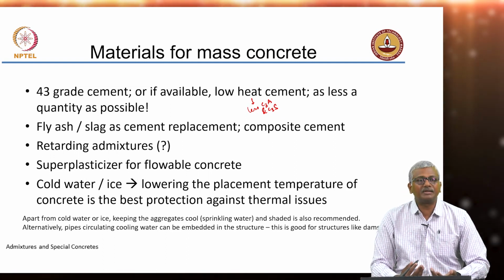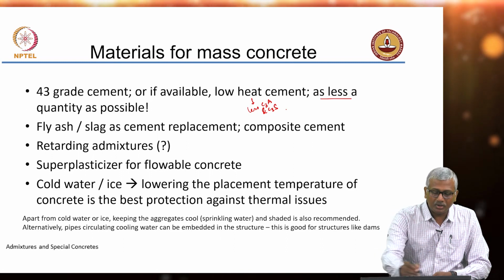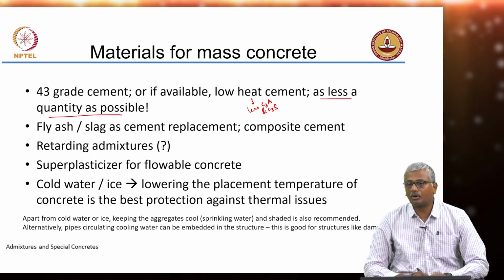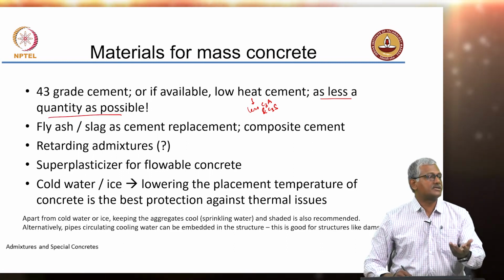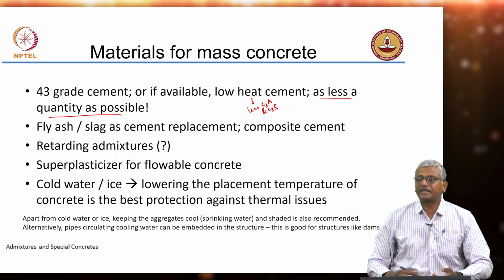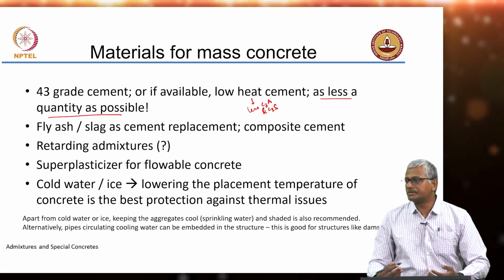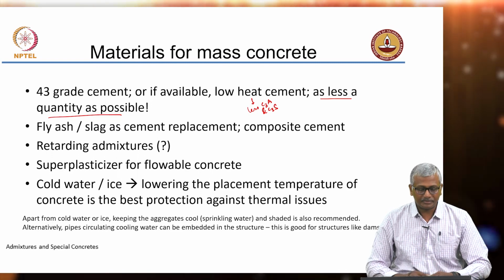Now, other thing to realize is that to keep the heat of hydration down, cement is the only one which is creating this heat, right. So, as less a quantity of cement as possible in the concrete. So, once again you can adopt strategies like particle packing, right. Maximize the aggregate content, minimize the cement that you put in your system.